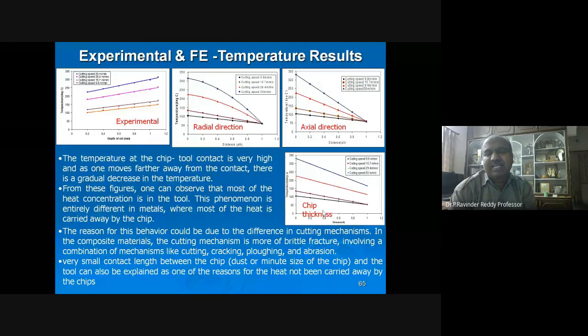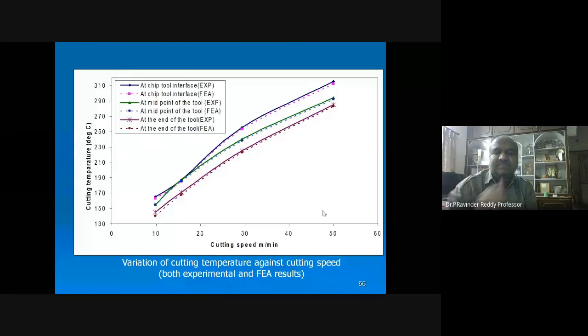In composite materials, the cutting mechanism is more of brittle fracture, involving a combination of mechanisms like cutting, cracking, ploughing, and abrasion. These are the four mechanisms observed in the cutting process. The very small contact length between the chip, dust or minute-sized chip, and the tool can also be explained as one of the reasons for the heat not being carried by the chips.